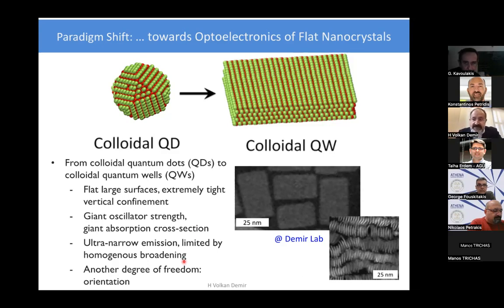Additionally, having this magic size allows us to also have quite narrow emitters. And indeed, for most of the chemical routes, we observed we are limited by only homogeneous broadening. So the exciton lifetime determines the absorption peak width, and the emission is actually quite narrow, as I'll show you. Finally, as I already mentioned quickly, now that we have these quasi two-dimensional structures, we can choose to orient them in 3D space, such as face down or edge up, or alternatively, their combinations.